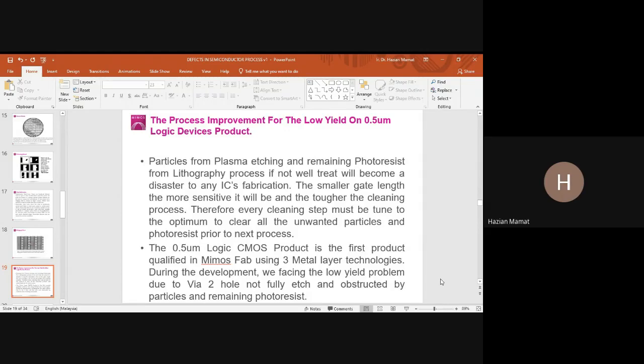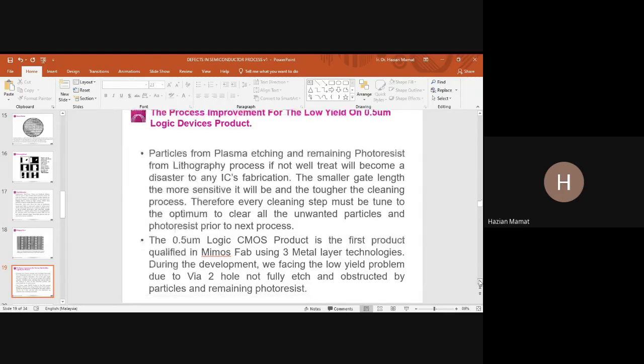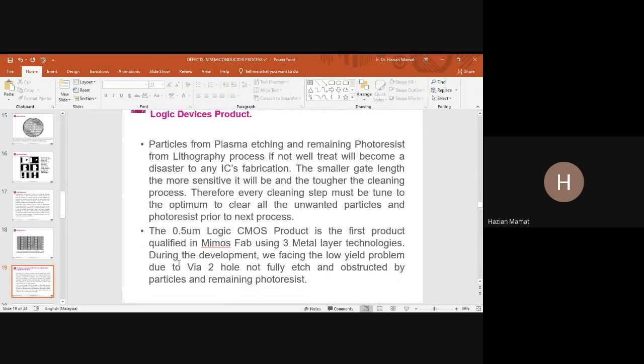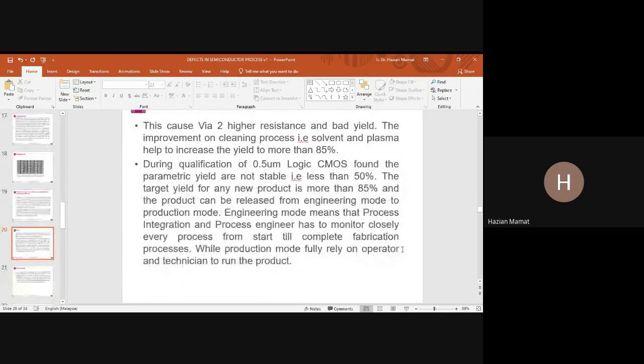During the development, we were facing a low yield problem due to the via hole not being fully etched and obstructed by particles and remaining photoresist. This caused the via2 higher resistance and bad yield. The improvement on the cleaning process, i.e. solvent and plasma, helped to increase the yield to more than 85%. During the qualification of 0.5 micron CMOS, we found the parametric yield was not stable, at 50%, while our target for the new product is more than 80%.